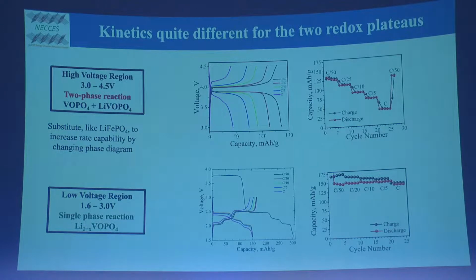So one of the things we do with this is look at kinetics. How fast can we get these reactions to go? What are the reaction mechanisms? And we found a number of issues. First, if you look at the top one here, you'll see that the capacity falls off very fast as we increase the rate of reaction. So that's this one here. So C/50 means it takes 50 hours. C is 1 hour. So you can see here's our capacity just falling off extremely fast. It is not a high rate material.